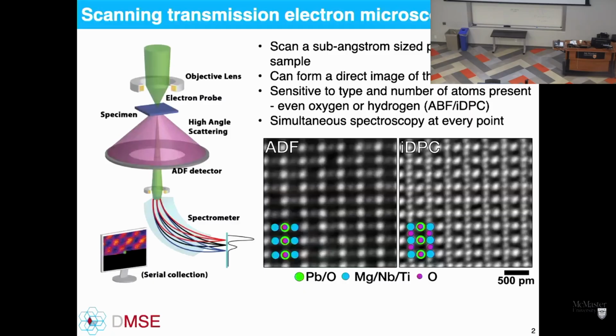And that is the technique of choice that we've had in my research, scanning transmission electron microscopy, where we used to use an objective lens to scan a very finely focused probe on our sample, sub-angstrom size, and collect images on a point-by-point basis. So you built up the image in a serial manner, and you could do spectroscopy at the same time. The key thing about these techniques, though, is that you could build up a direct image of the structure, where in annular dark field imaging, for example, the brighter the atoms are in the image, the heavier they are. And the downside is you lost all ability to see light elements like oxygen, nitrogen, many of the key actors in ferroelectric and functional oxides that make that functionality possible.